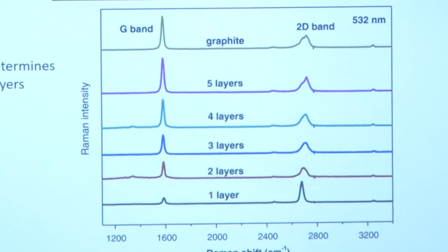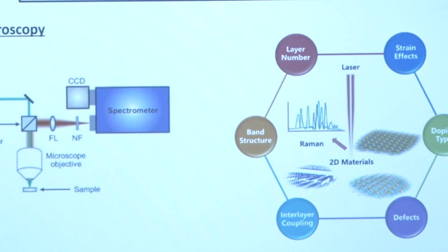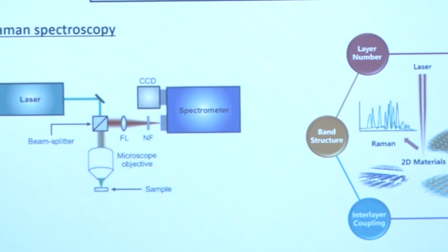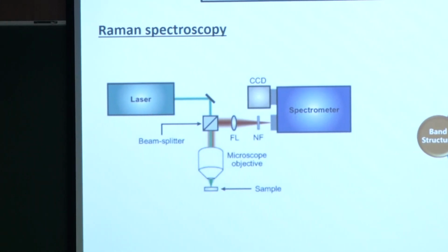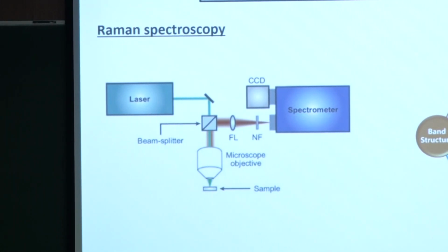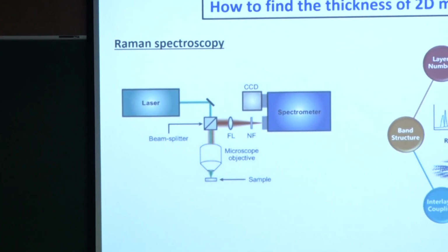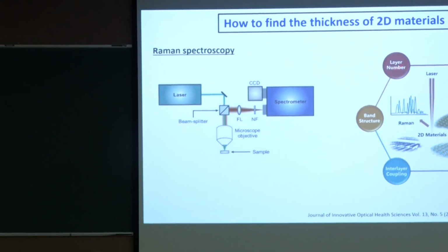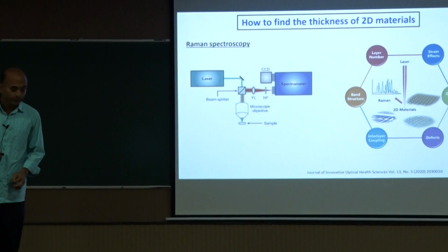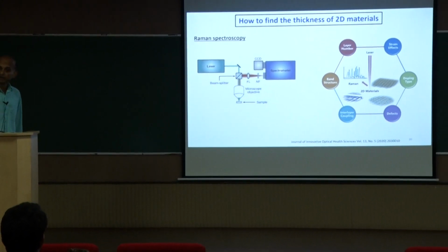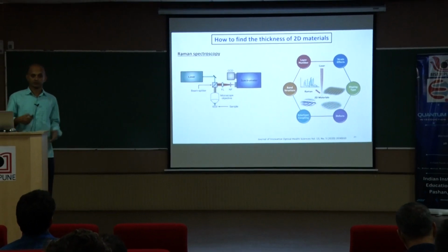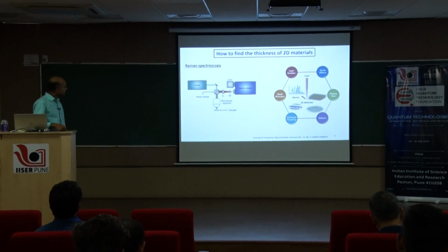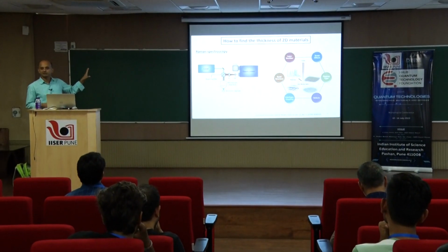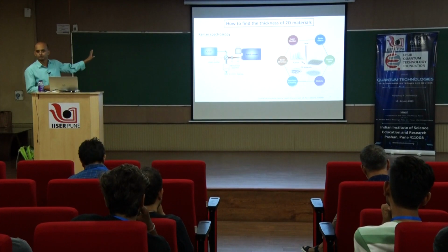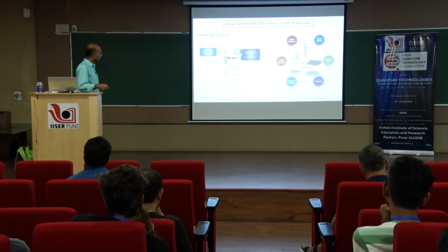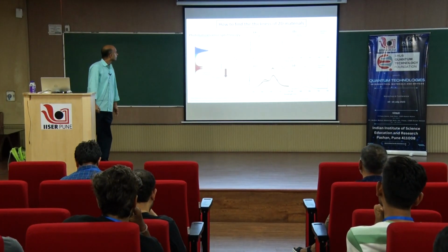So this is one of the most common and popular techniques, because not only the thickness can you determine using Raman, you can also identify if there is an effect of strain, what is the type of doping, whether you have more defects or fewer defects, or what kind of defects are there, interlayer coupling, band structure. So you can see why Raman spectroscopy is so popular these days, especially in the 2D community.